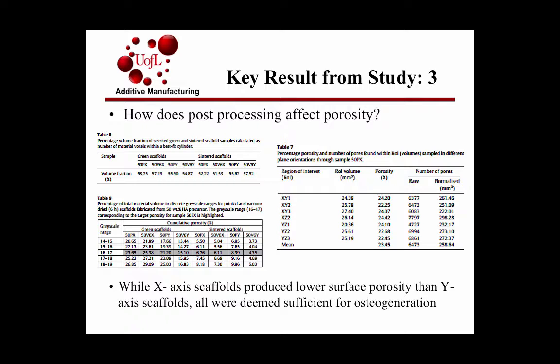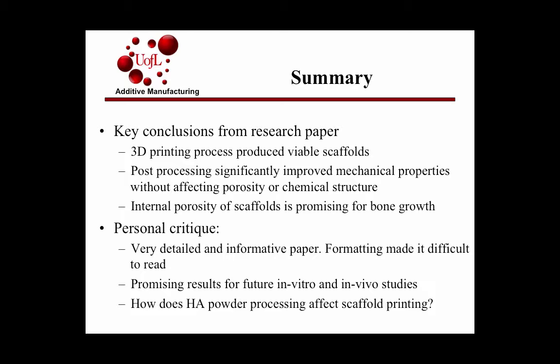And you can see the number of pores is relatively consistent, this is for one sample, across the different areas of the sample. And the x-axis parts showed a greater volume fraction of, I want to say, HA than the y-axis samples. So in conclusion, they just said that the 3D printing process was viable to produce bone scaffolds. Post-processing significantly improved the mechanical properties, making it stronger than just a pile of powder. And internal porosity of scaffolds is promising for bone growth because of the surface roughness.